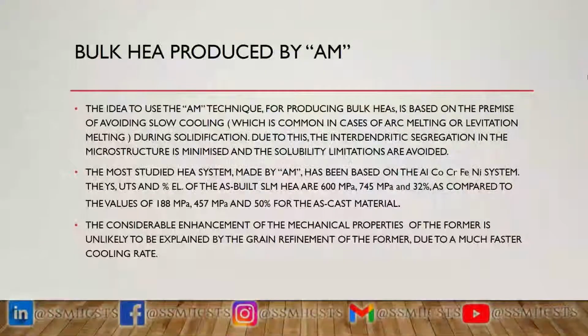The most studied high entropy alloy system made by AM has been based on the aluminium, cobalt, chromium, iron, nickel system. Look at the yield strength, UTS, and percentage elongations of the as-built, laser melted HEA. Yield 600 MPa, UTS 745 MPa, percentage elongation 32. And look at the comparison with that for the as-cast material the normal way, where the yield is 188, UTS is 457, and of course, the elongation is more, 50%.